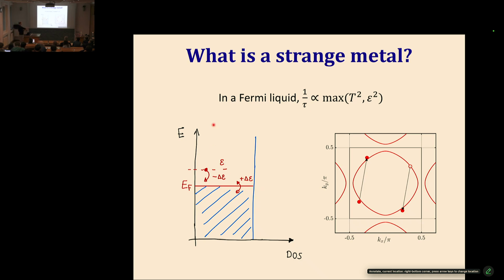That's actually the argument. And as mentioned by Michael, this is sort of a leading order calculation. But the beauty of Fermi liquid theory is that that actually extends all the way to intermediate and even strong coupling. So the coefficient of this T squared and epsilon squared term is hard to calculate, but the power law is very robust. And that really is one of the telltale signatures of a Fermi liquid. Now, of course, let me stress, just seeing T squared or epsilon squared does not mean that this is the right picture, that it's a Fermi liquid, that this is the right mechanism, and so on. There are actually mysterious puzzles in condensed matter where we see this T squared and epsilon squared behavior where we don't expect them. But any violation of this law means that something about this simple phase space argument has to break down.